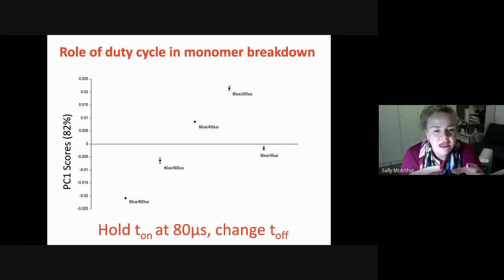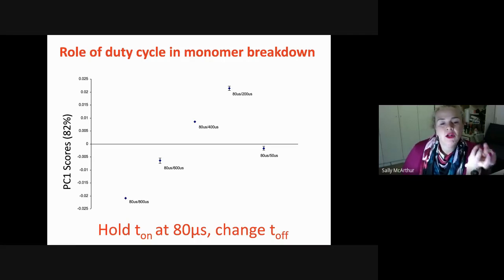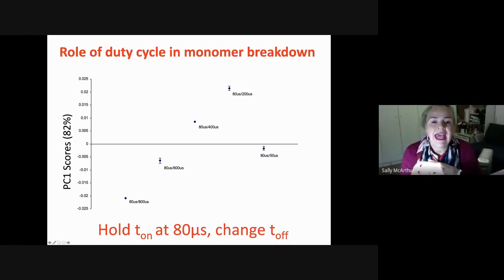We can keep our on time the same and constant at 80 microseconds, but if we change our off time, how does that actually affect the monomer and the monomer breakdown process? So we're holding our time on and then changing our time off. Now, obviously, that affects the duty cycle and the amount of power in the system. But if we look at it, we can clearly see with the TOF-SIMS, by analysing the coatings that are produced from those, that it quite neatly separates out each of the chemistries. So there are variations in chemistries with those off times being varied.